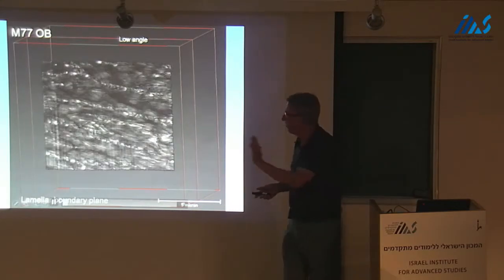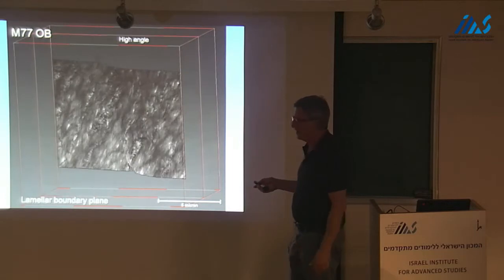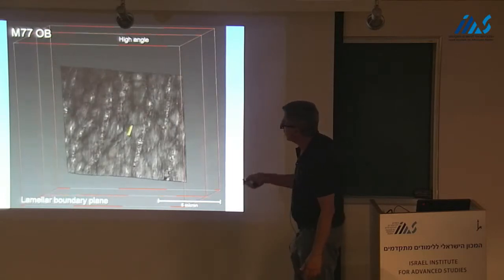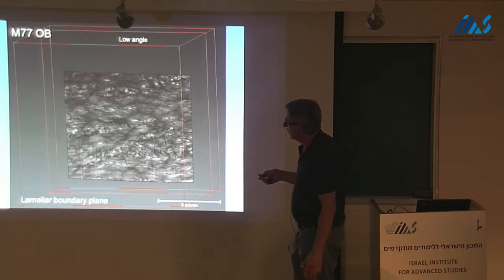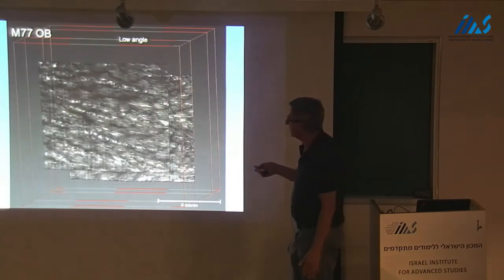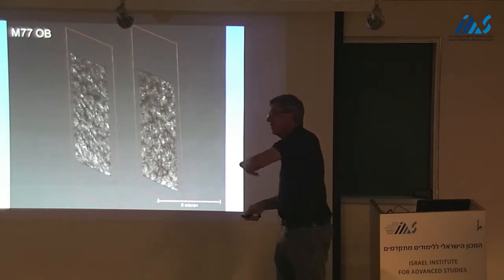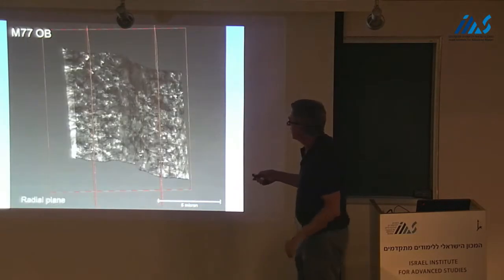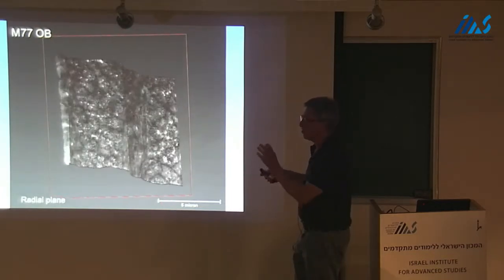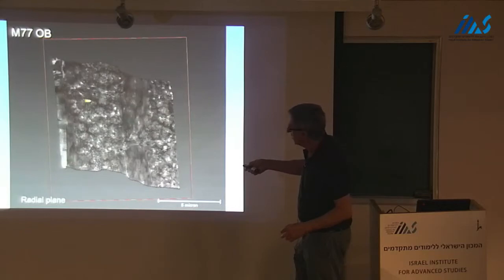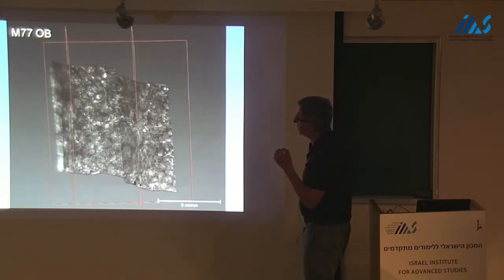This is now going through the whole stack, and you can see there's the disorder, sort of chaos. And then it changed direction. You can see these thin layers, chaos. And then you can start seeing that it's now flipped back to being more or less horizontal. You have this direction, this direction, and it changes. Now you're looking end-on. You can also see that these collagen fibrils that are in arrays are actually arranged in bundles, which was another aspect of the structure which was not recognized before.